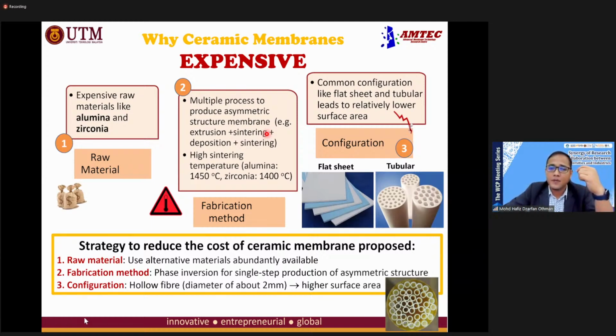So this is one of the efforts to reduce the ceramic membrane cost. For example, we can use alternative materials that are abundantly available, and we can also use a fabrication method like phase inversion, which can produce an asymmetric structure in a single step. And also we are able to produce a hollow fiber membrane. Once we use phase inversion, we can also produce a smaller version of tubular, what we call hollow fiber, and the diameter of this membrane is less than 2 millimeters. And this is the diagram of this hollow fiber if we make them in a module. So therefore, we can increase the surface area of the membrane.